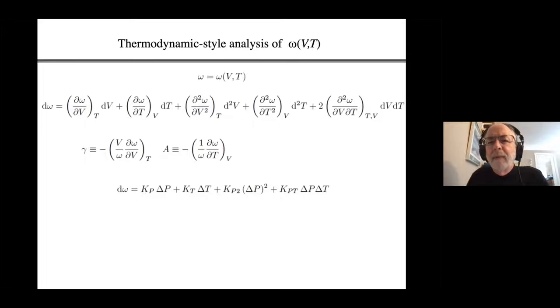So that's one of the things that you typically do in ab initio calculations, is you figure out what the distances are between your atoms, and the electrons find states according to that. But we've also got temperature, which is how much they're vibrating about their official positions. So we'll use both of those variables in this expansion for the d omega as a function of first order terms. How does the frequency change with volume?